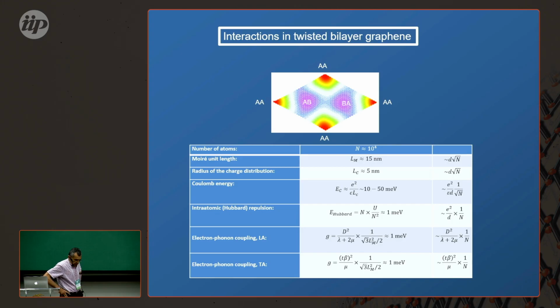And then what stands out is that as you increase the size of the moire unit cell, the effective interactions between electrons in the famous flat bands change. Let me emphasize that within these moires, all the action is localized into flat bands, which contain between 0 and 8 electrons in total.